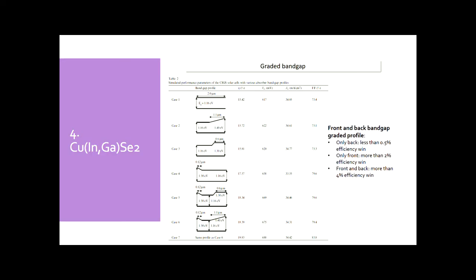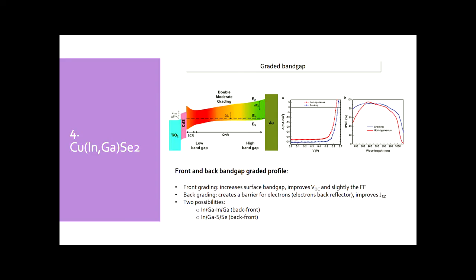The second important effect for increasing the efficiency of CIGS is the gallium alloying. So you can try to introduce gallium. Gallium compounds have a wider band gap at the front, at the back, and all the combinations possible. And with some of them you can gain even up to 4% efficiency. And this is the typical grading that is used in CIGS. It's a wider band gap at the interface with the cadmium sulfide and a bit wider band gap at the interface with the back contact.